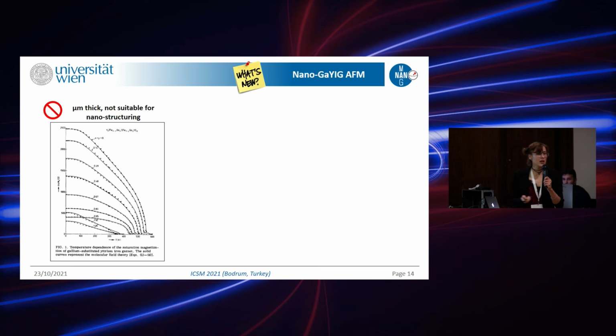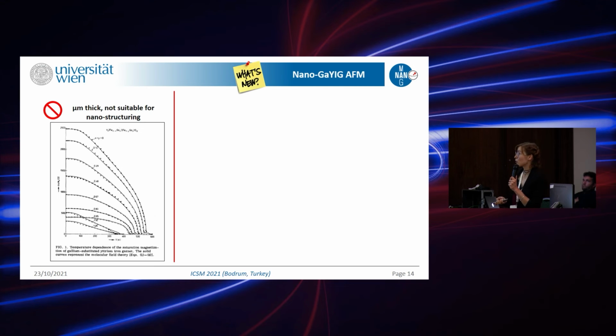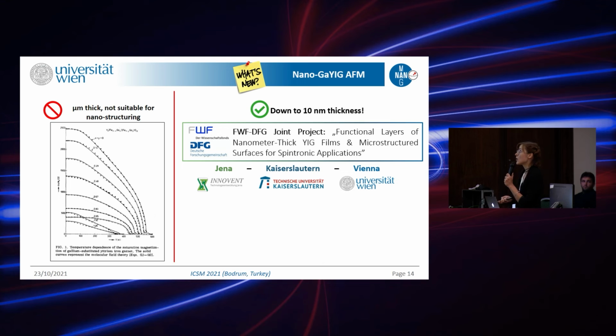But why wasn't it realized up to date? Well, in this old article, and for a long time, there was no breakthrough because it was a micrometer thick material. And with the latest results that were obtained amazingly by Dr. Dupes, we are able to have materials down to 10 nanometer thickness.